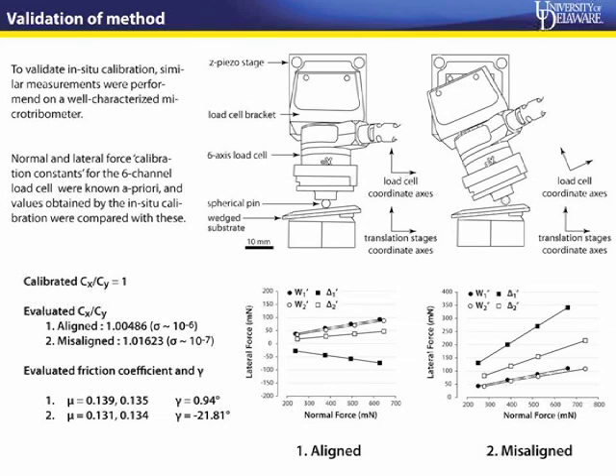You'll also notice that for the aligned case, where the transducer is aligned with the translation axis, and the case where it's misaligned with the translation axis, for both cases and both angles in each case, the friction coefficients are really close. What's also interesting is that gamma for the second case accounts for the transducer misalignment. Gamma came out in this case to be -21 from the solver. That tells us that gamma is accounting for the gross misalignment that you have with the transducer.